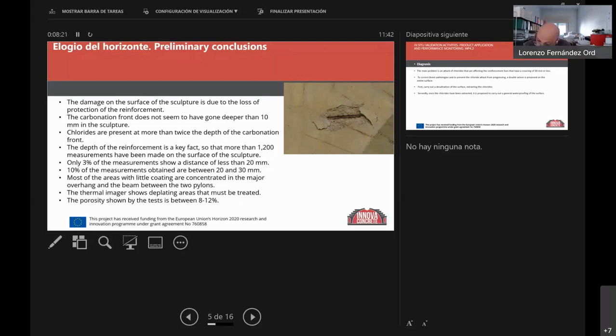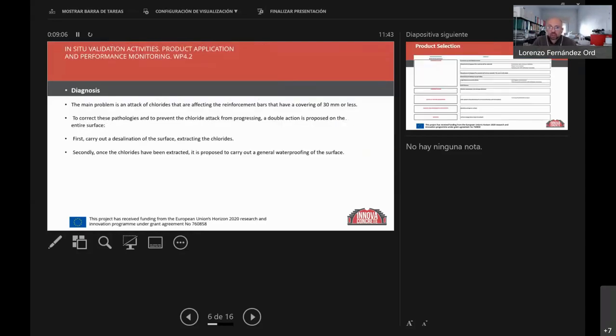less than 20 millimeters. The form is rounded, and it seems that in some cases the bar didn't stay in its place when they poured the concrete, so there was some kind of construction problem there. But the main areas have more than 30 millimeters, and they were not attacked yet by the chlorides. So our diagnosis was that the main problem, as I said, is the attack of the chlorides, which affect the reinforcements in the areas with less than 30 millimeters of depth.